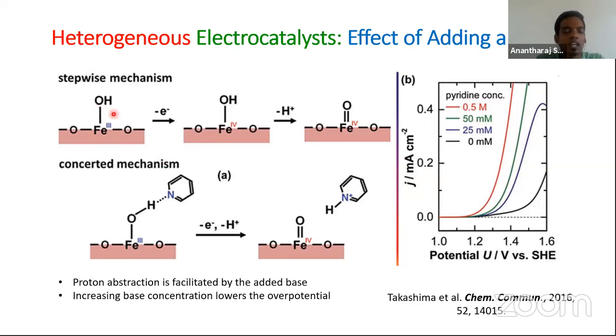They proposed a stepwise mechanism when they don't use any base, but when they used a base like pyridine, it assisted the deprotonation step. And this particular two-step reaction has occurred in a concerted fashion. I mean, the proton abstraction and electron release both had occurred at the same time, so that the catalytic material becomes efficient in oxidizing water. And they also proved it by increasing the base concentration in a way by which not affecting the overall pH of the buffered solution. As you can see, when there is no base at all, very low current density and the overpotential is very high.